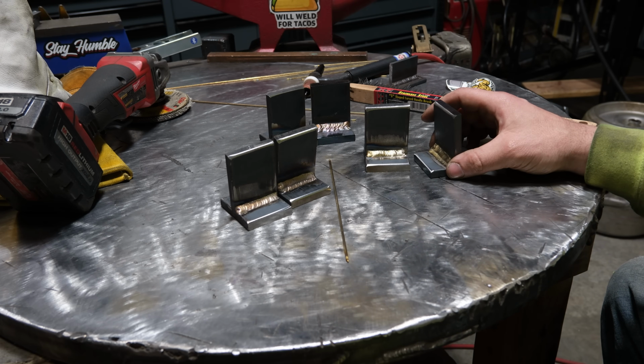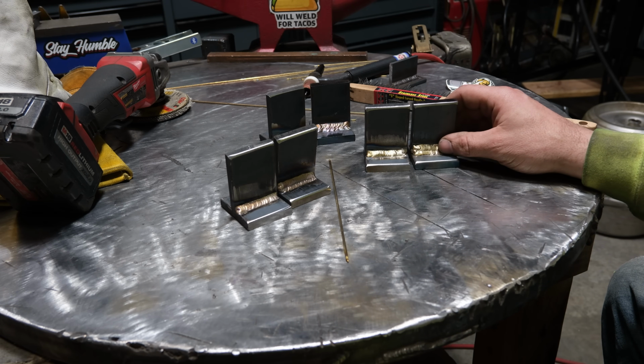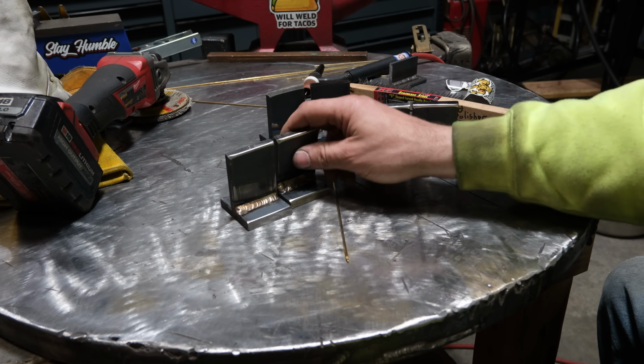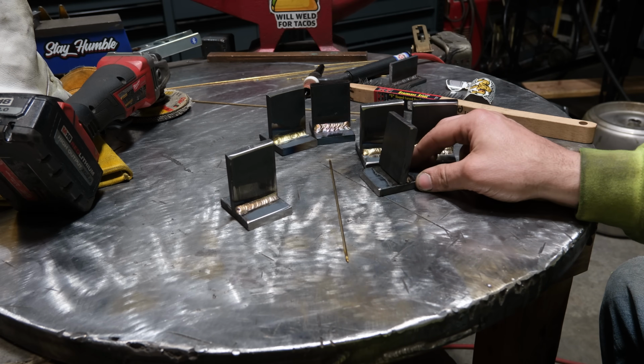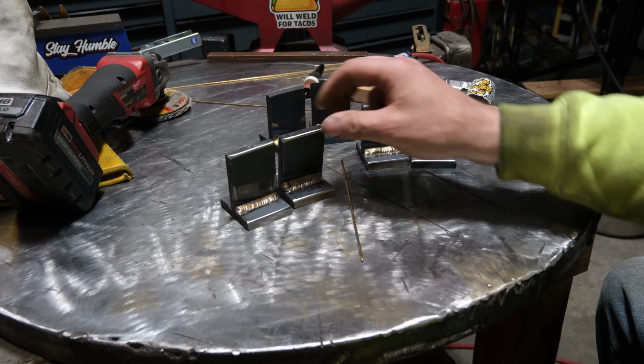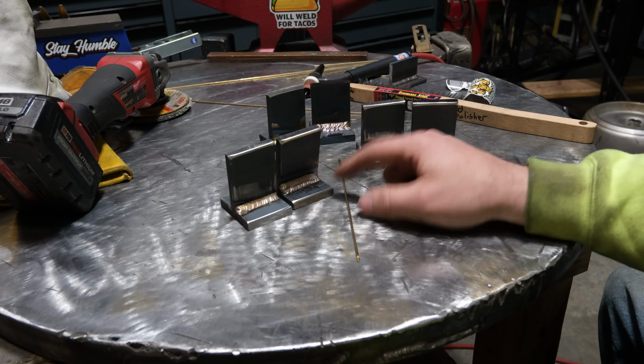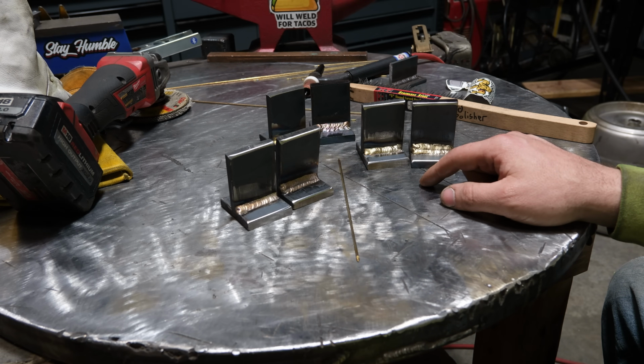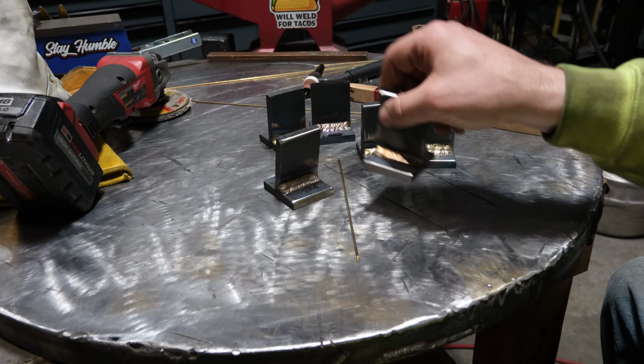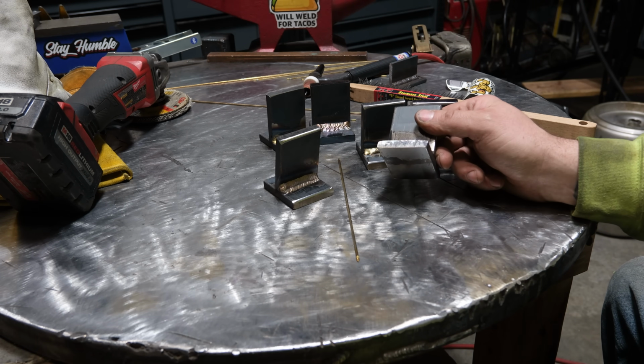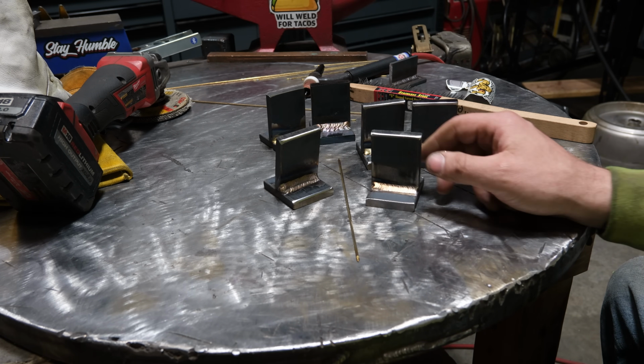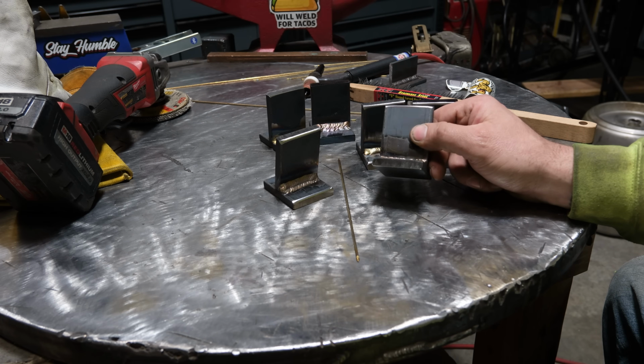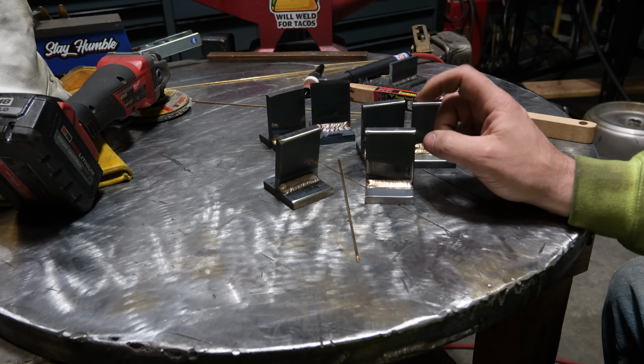Like this aluminum bronze pulled a little bit, being a multiple pass weld, but not nearly as much as this silicon bronze. So it seems to shrink a lot more in what I'm seeing with the silicon bronze. Well, with that said, we're going to bend these away from the face just like I would a normal weld in the shop press,